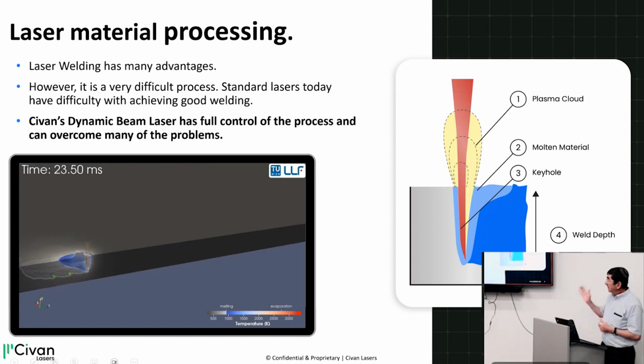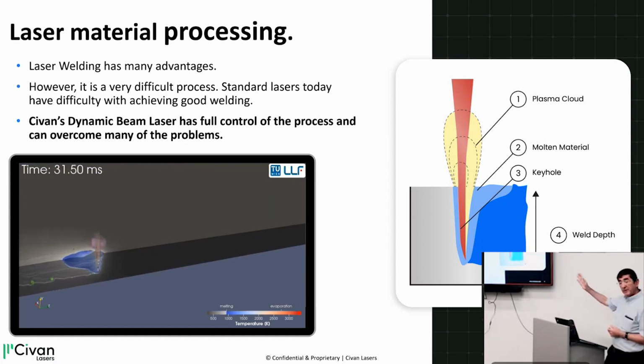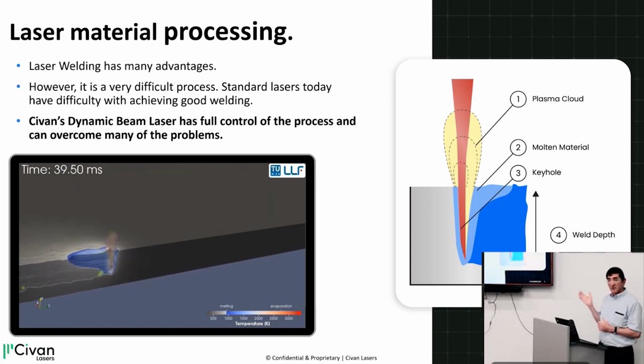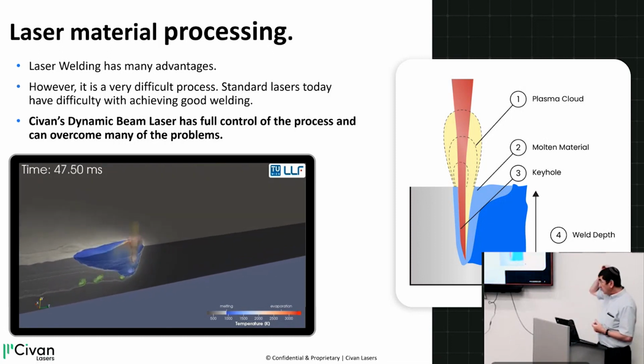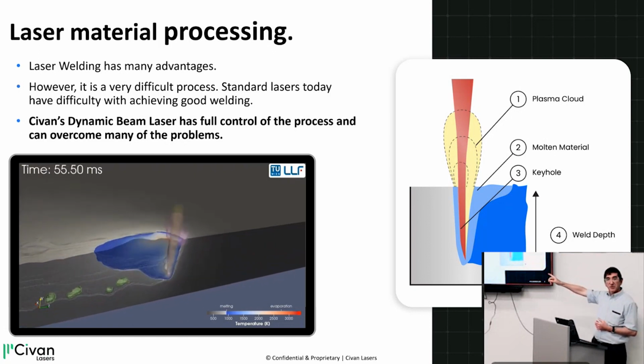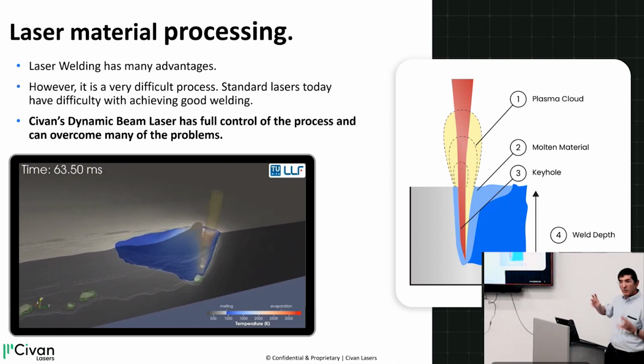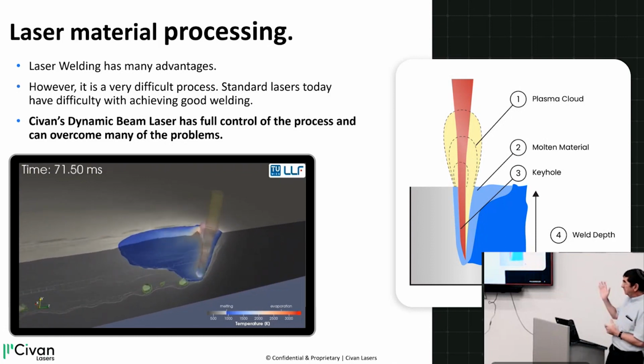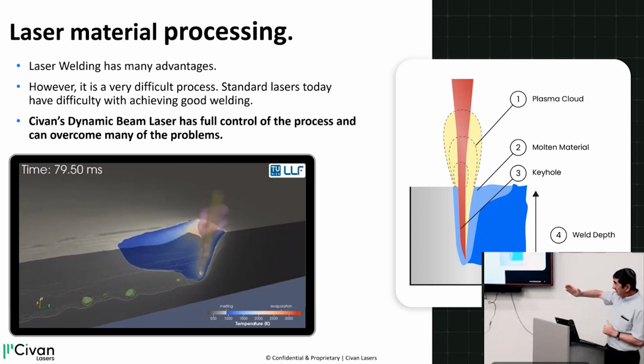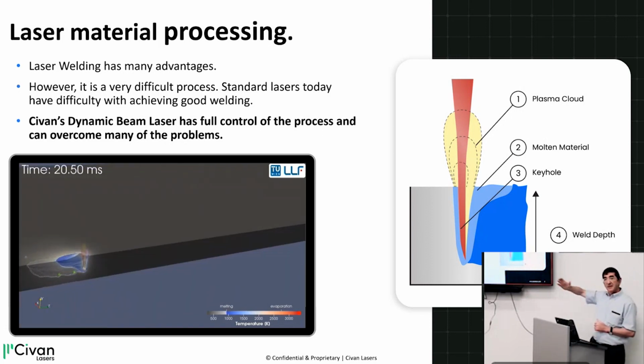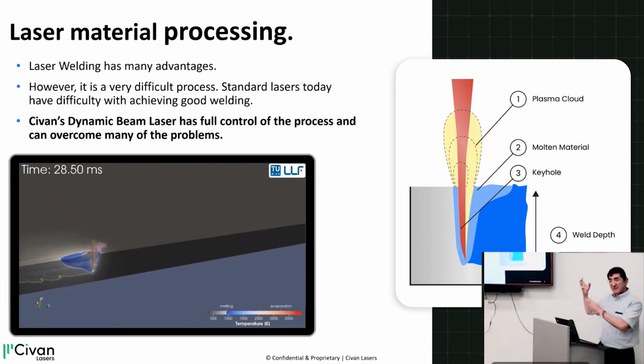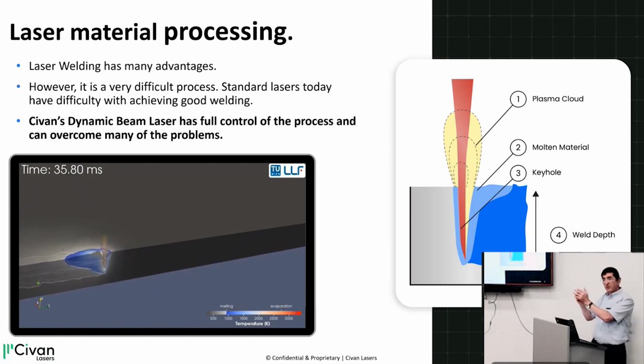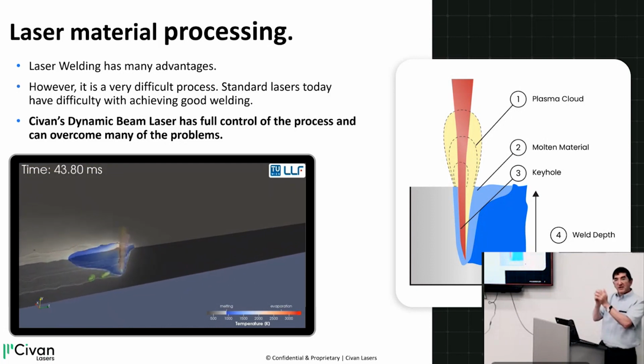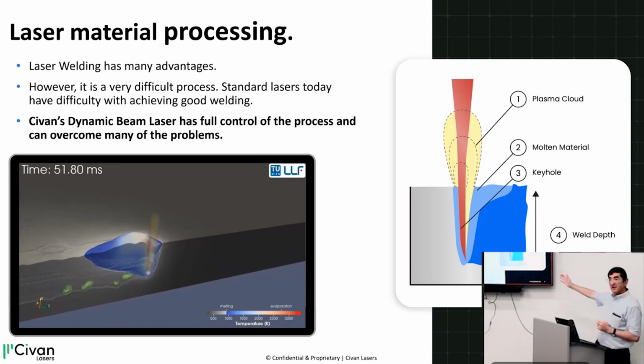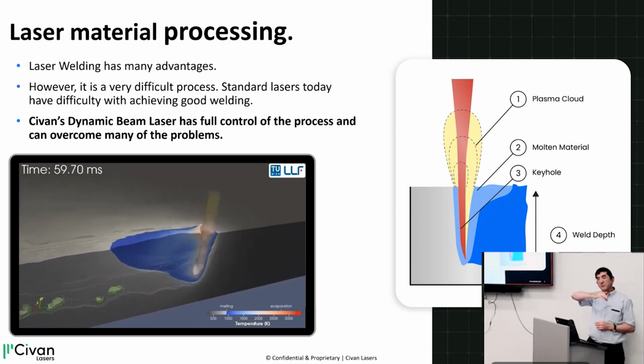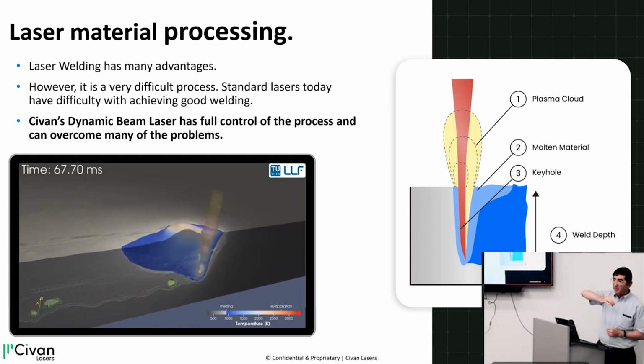So this is a simulation. Many of the simulations you'll see here are done by the Technical University of Vienna. It's a very, very detailed simulation. This 100 milliseconds simulation takes about 2 weeks to calculate because it takes all the physics that are happening here into account. It's a very, very precise simulation. So what you see is that we can weld here, and in a few milliseconds, the metal goes from solid to liquid to gas, and then cools off to liquid and to solid again. All this in milliseconds. So for example, we can go 30 meters per minute and weld something. Okay, that's 500 millimeters per second.